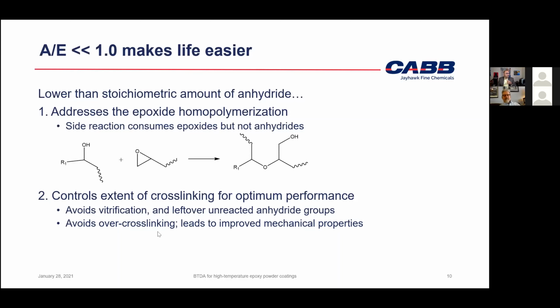Exactly. So basically, between the issue of vitrification, which Kevin, you mentioned, and then on top of that, you have the issue that BTDA, by its very nature, will cross-link a resin to a very high degree, or at least have the potential to cross-link to a very high degree should vitrification not occur. And if you did complete all those reactions, you can have what we will call over cross-linking. You may have a very tightly bound network, which doesn't have the physicals your coating needs. So for that reason also, it's best to go way off ratio, and we'll give you some examples of how much we're talking about. And that way, the excess epoxide that is in the system will have a chance to homopolymerize and consume itself, and your system will be better optimized that way.